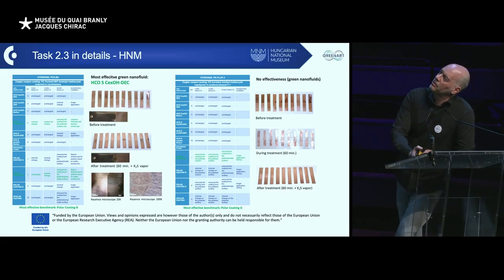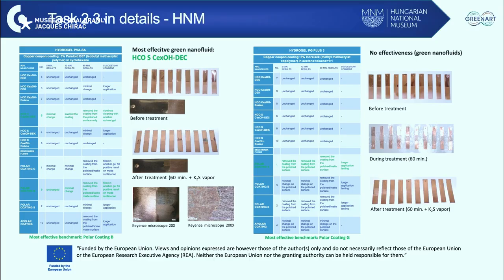So these were some of the results we could get. It's really hard to see on the screen for me, but as far as I remember, we loaded the different gels with the nanofluids, and the example you can see here is a PVA type of gel, and we also use the benchmark for this cleaning, which is Polar Coating B. And the most effective, because some of them were really effective, of the new green materials was the diethyl carbonate, the DEC type of nanofluid. We put these coupons after the removal into a high concentration of potassium sulfide vapor, so we could clearly see the differences and the effectiveness of the cleaning of the gels. But on the other hand, during the removal of the Incralac, we could not observe any effectiveness of the new green materials.